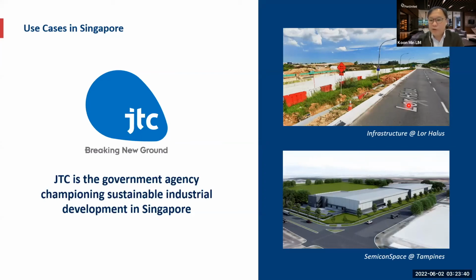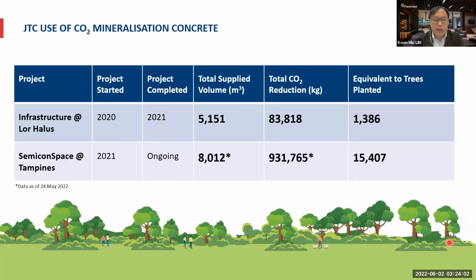And after successfully using this, for the next project, Semicon Space, they have in fact specified the 100% use of CO2 mineralized concrete in their Semicon Space project. And not only that, they have also specified the use of green cement at 30% replacement of ordinary Portland cement in their project. And quickly, I shall go through the CO2 savings they have achieved compared to if they hadn't used the CO2 mineralized concrete and the GGBFS.